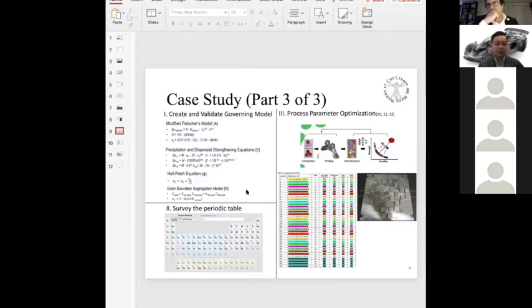So we own the whole process, from modeling the alloy and choosing what's most likely to succeed, and then we outsource the powder making part. Once we have the powder, we optimize our process parameters. That was quite an iterative process. I think we've tried over 200 different compositions, and we were able to succeed in 2 families, 2 series of aluminum for high strength and ductility.